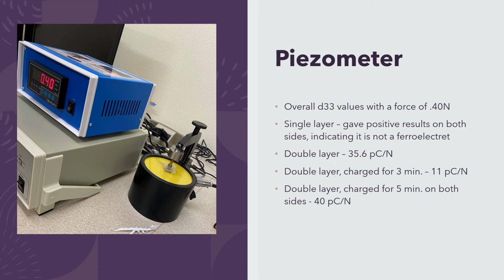During the analysis portion, using the piezometer, a force of 0.40 newtons was applied to secure the sample during testing. And to find a D33 value, the sample is measured once and then flipped over and measured again. If the material is a ferroelectret, then the value should be positive on one side and negative on the other side. And to find a D33 value, you calculate it by taking the absolute value of the first measure and then adding it to the absolute value of the second measure and dividing it by 2.